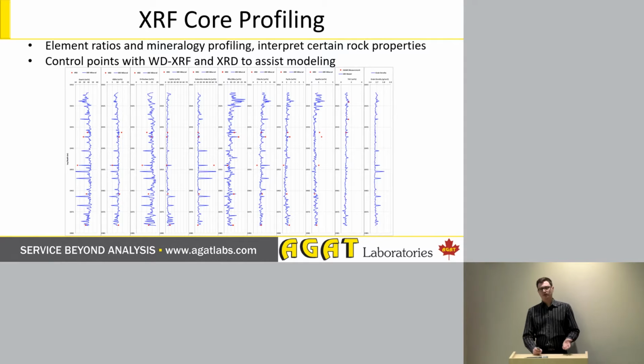So this type of data, when you're doing profiling, each individual point is considered semi-quantitative because we're trying to interpret mineralogy from elemental chemistry, which is a non-trivial process. However, what we do is throughout a core, we would tend to calibrate the XRF profile using control points where we have wavelength dispersive XRF for a much more accurate analysis of the elements, and XRD for a more accurate analysis of the minerals. This allows us to have confidence in our XRF profile that we then generate.